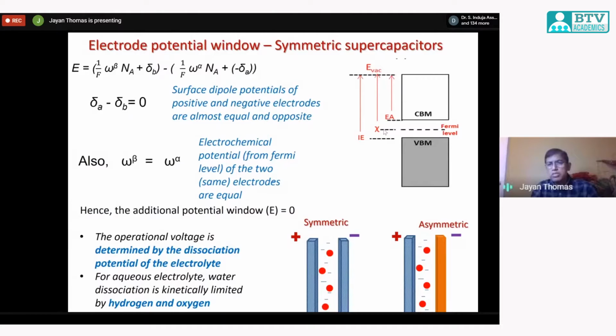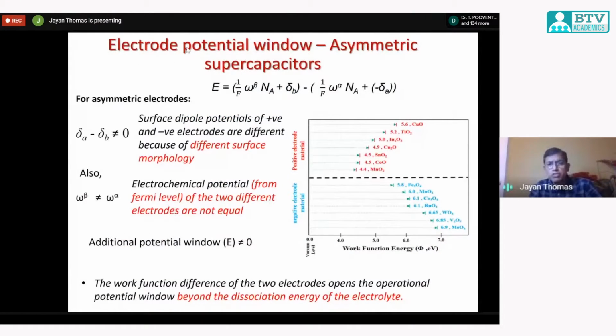Here I am just showing you the work function. That is the energy from vacuum to the Fermi energy level. This is the work function, this is the electron affinity, and this is the ionization energy. But in the case of the electrode potential window for the asymmetric supercapacitor, you can see that these are two different materials. So delta A minus delta B is no longer equal to 0, and omega beta is no longer equal to omega alpha. The electrochemical potentials are different, as well as the surface potentials. Now it is no longer dependent on the decomposition potential of your electrolyte, but it depends on the work function difference of the two electrodes. That is the key point you need to remember. Now your voltage window is dependent on the work function difference of the two electrodes.